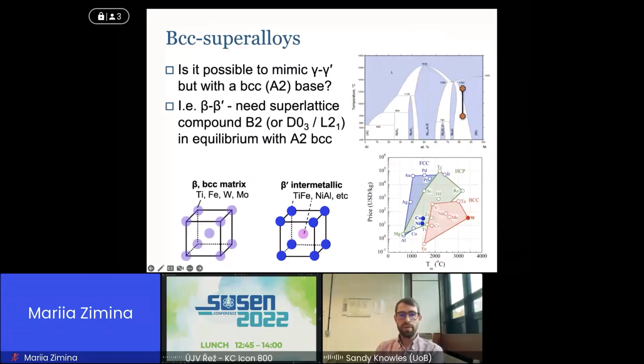So we have our BCC unit cell that people may be familiar with. There's lots of different metals that we can have as our base BCC matrix. And then we can consider, well, what is a beta prime intermetallic? Well, the simplest one is what's called the B2 crystal structure, where the center atom is ordered and your corner atoms are different species. So things like titanium iron, or more commonly nickel aluminium. There was a huge amount of work on monolithic nickel aluminium, so nickel aluminides, through the 90s for aerospace applications.